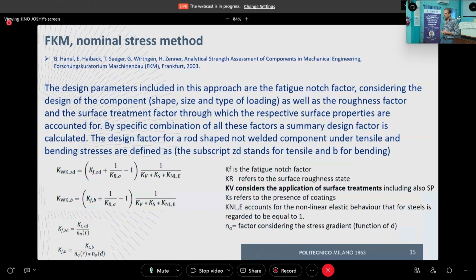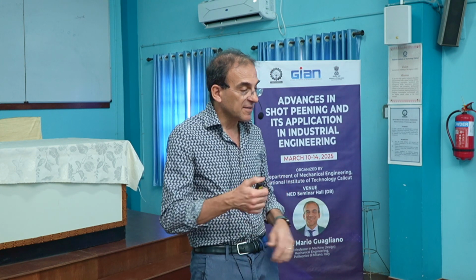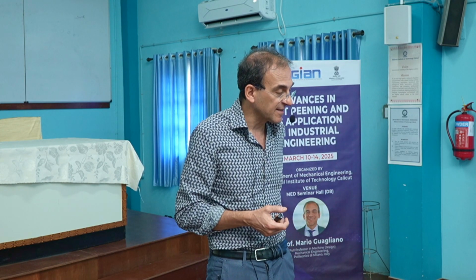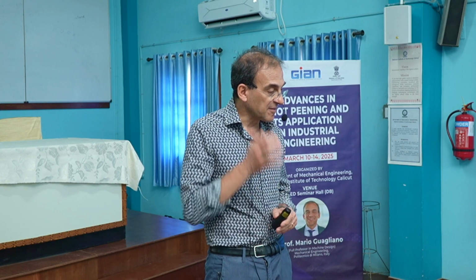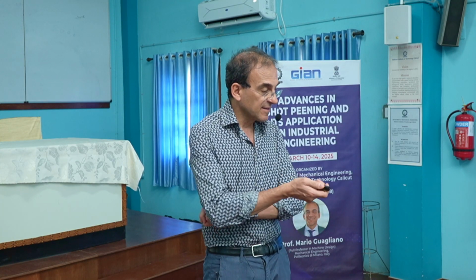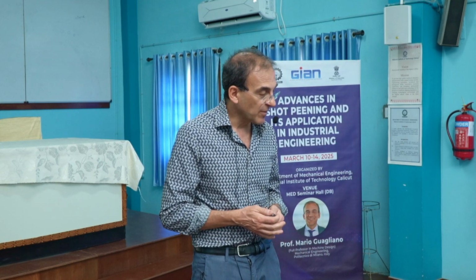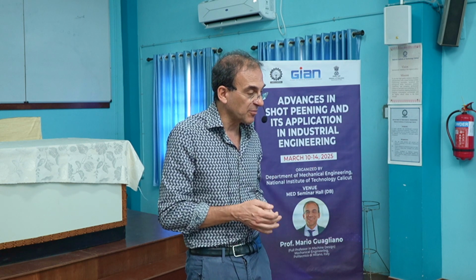They say that if we have to deal with fatigue, I'm talking about the nominal stress method, we consider what makes the case of interest different from the standard samples. So the fatigue strength of the material is adjusted by means of factors, coefficients. So we have shape, size, type of load, roughness factor, and surface treatment factor that are considered. And by a specific combination of these factors, a synthetic, let's say, design factor is calculated: K_WK, Z, D, or B. The design factor for a rod-shaped, not welded component under tensile load is defined this way. So if we refer to not welded details, we can define this design factor that includes all the different contributions in this way.